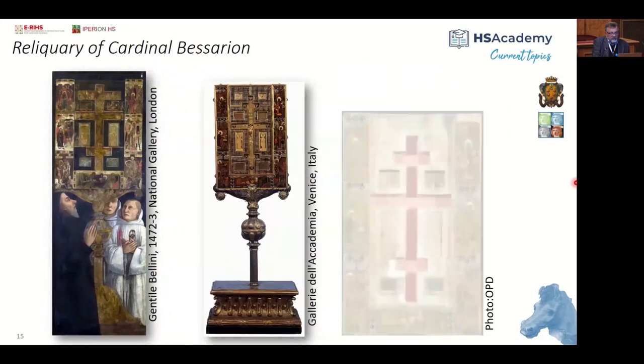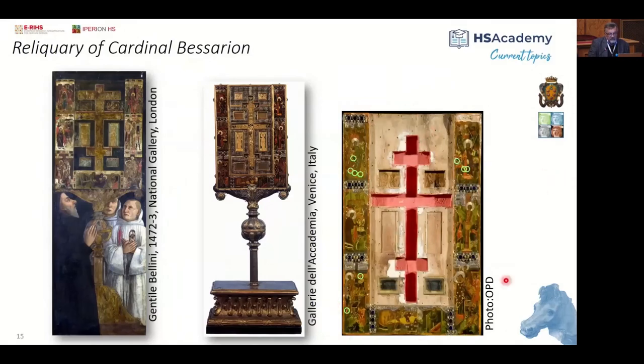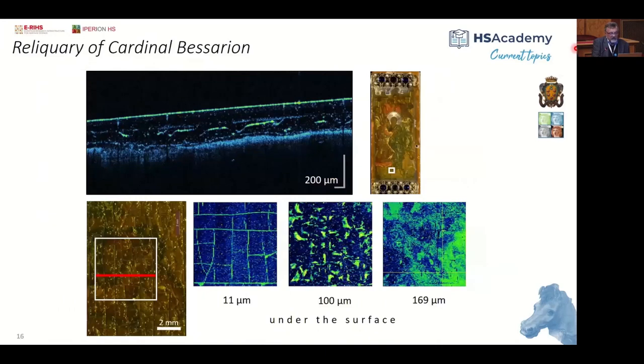Okay, so we're working on the painting structures here. And the first thing I want to show you is again these parallel cross sections. The first one is just a crackle, these little cracks at this level. Then if you go down, we see these internal cracks in the very thick layer of varnish, due to exposure to sun. And below is the paint layer. So this was again a hint for the restorer that this process, which is visible on this paint, is located inside the varnish, not related at all to the original paint layer.